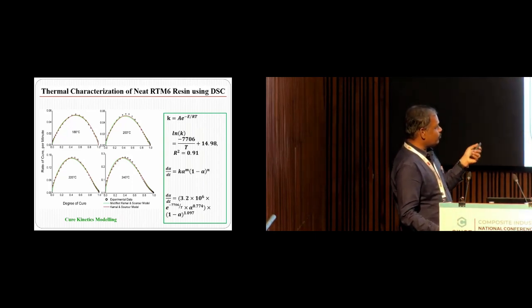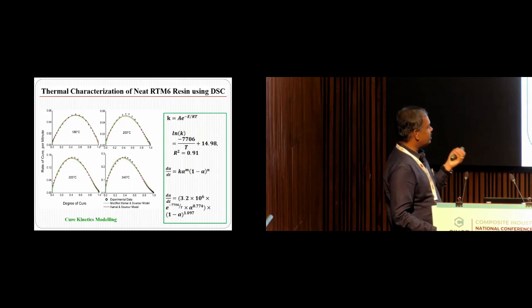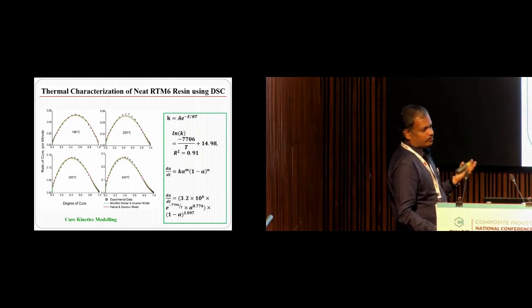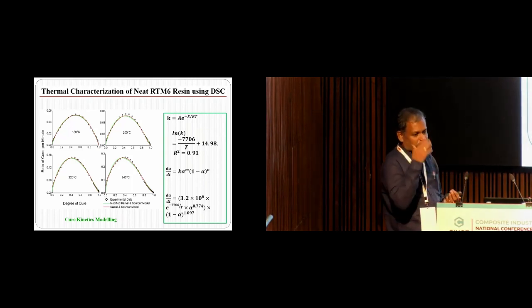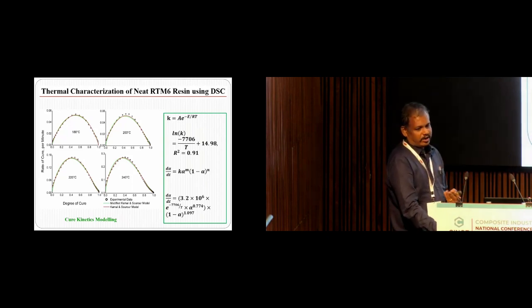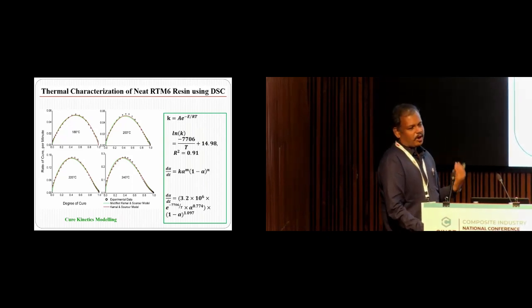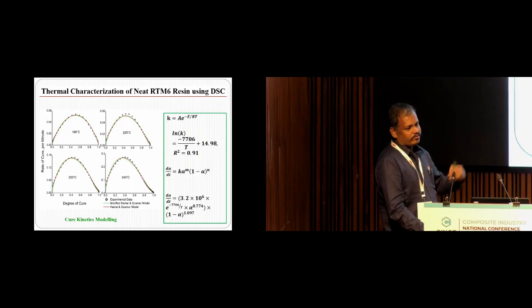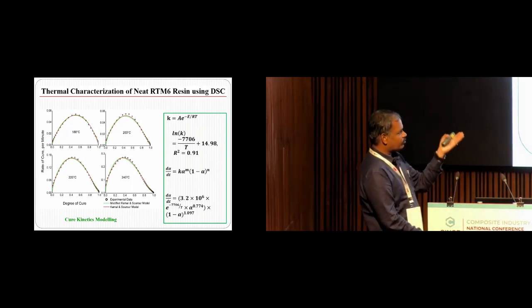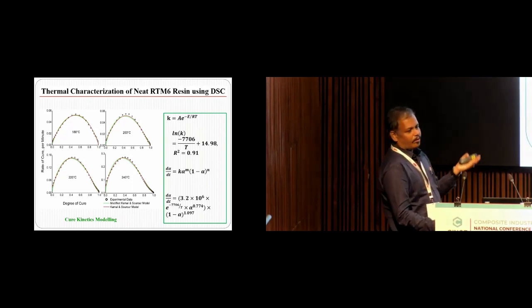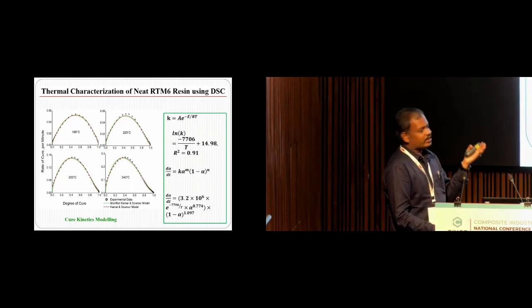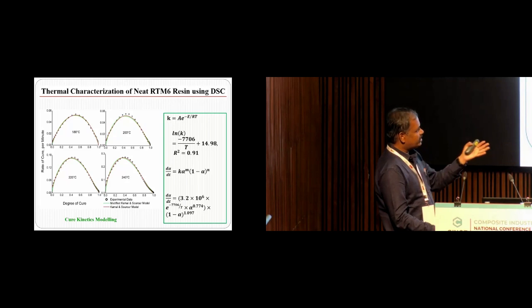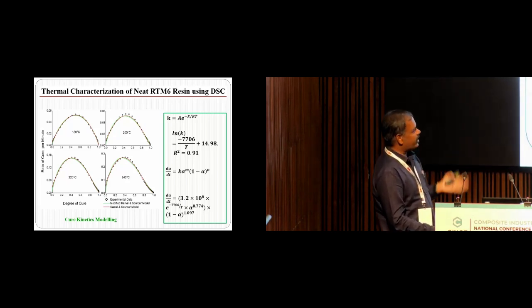That rate of cure is plotted as a function of degree of cure to fit into classical cure kinetics modeling. Here we fit two different models. One is the Kamal and Sourour model, which is a 4-parameter model, and the other is the modified Kamal and Sourour model, which is a 3-parameter model. Whichever model with the lowest number of parameters fits well is taken as the best model. Here the modified Kamal and Sourour model, dα/dt = k α^m (1 − α)^n, is taken as the ideal model, and it fits exactly, with a correlation coefficient of more than 0.9.